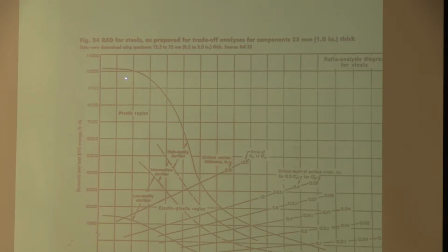At low strength steel, you can get very high toughness. As you go to higher and higher yield strengths, up to 300 KSI, your toughness goes down and your critical flaw size gets smaller and smaller. That's what these lines here are. Critical section thickness is 2.5 inches. So you could build a pressure vessel out of a steel with properties anywhere along this line, and it could be 2.5 inches thick, and it would leak before it breaks.